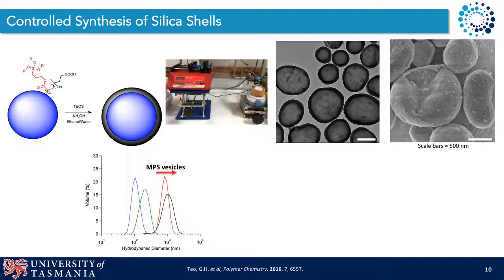Once we'd formed our nanoparticles, the next investigation that we performed was to grow, by controlled base catalyzed hydrolysis and condensation, our silica precursor onto the surface of our nanoparticles using a controlled feed method. And we can see here, both by the DLS distributions as well as TEM and SEM, that we form a uniform shell of silica, typically between 30 and 50 nanometers in thickness, on, in this case, our polymeric vesicles.